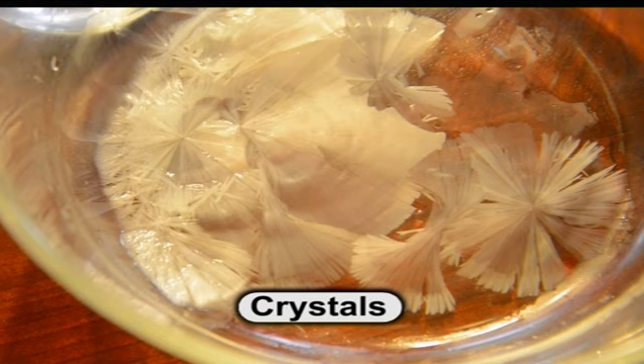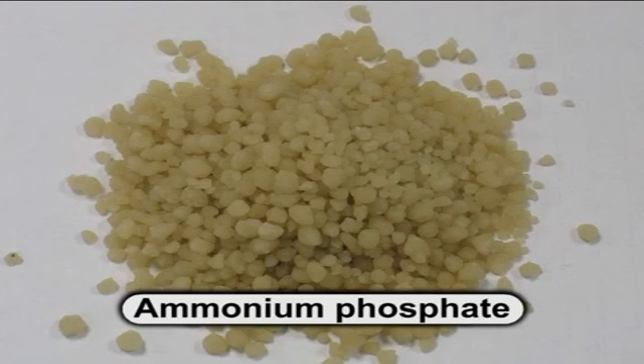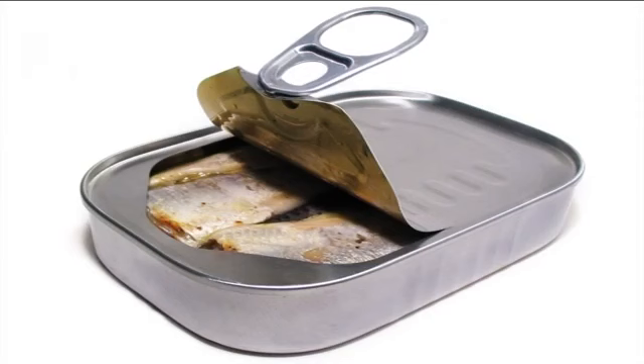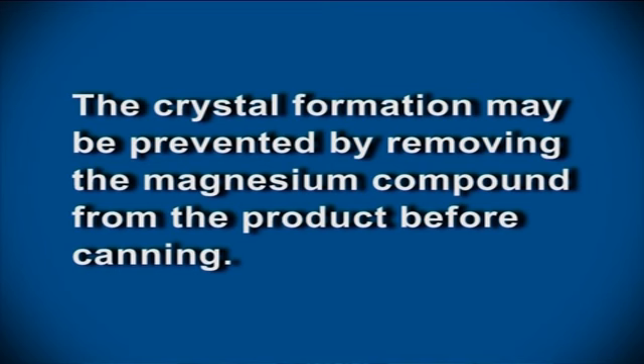Struvite glass-like crystals result from the formation of magnesium ammonium phosphate. Ammonium phosphate results from the reactions of magnesium in seawater and ammonia produced from fish muscle protein during heat processing. The crystals form after heat treatment during cooling period. Appearance of crystals gives an unpleasant appearance but seems to be harmless. The crystal formation may be prevented by removing the magnesium compound from the product before canning. This is usually achieved with the addition of chelating agent.